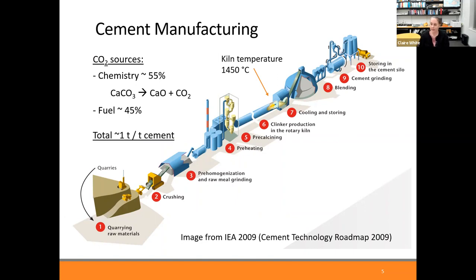Returning to cement manufacturing, why are there CO2 emissions associated with the manufacturing of cement powder? Well, if you look at the industry, what happens is you dig raw materials out of the ground. Limestone is one, which is calcium carbonate, and also clays. And you heat them up in the kiln to really high temperatures, 1,450 degrees Celsius thereabouts. And what happens at about 900 degrees Celsius is you get this decomposition of the limestone. It forms lime, calcium oxide, and then there's this CO2. The reason why we go to higher temperatures is for the formation of calcium silicate phases that are reactive with water. So we have to go to these really high temperatures to get the right phase composition in the cement powder for it to be able to react with water.